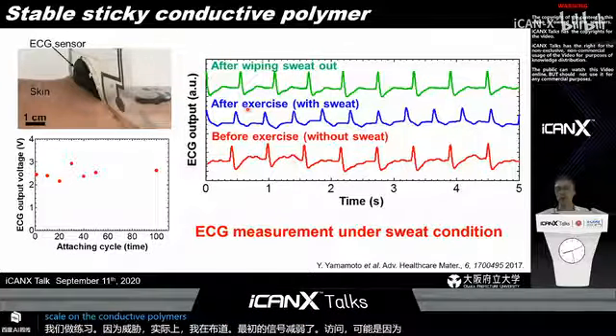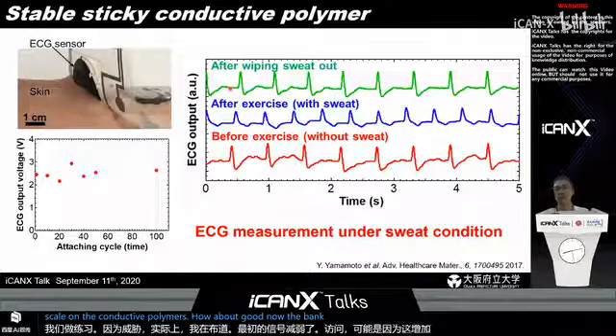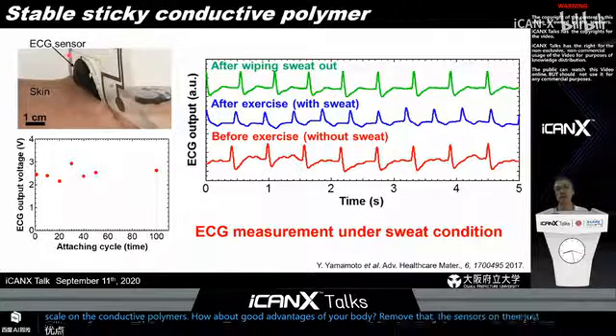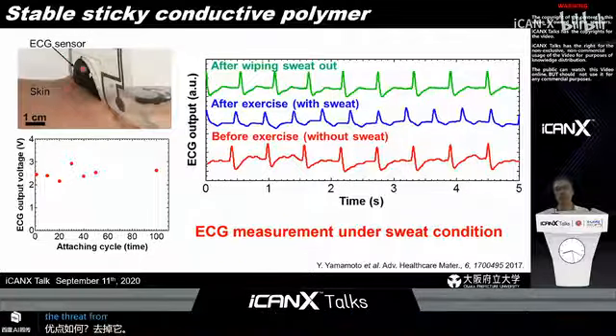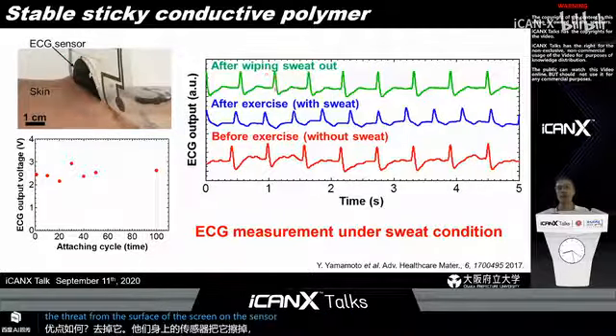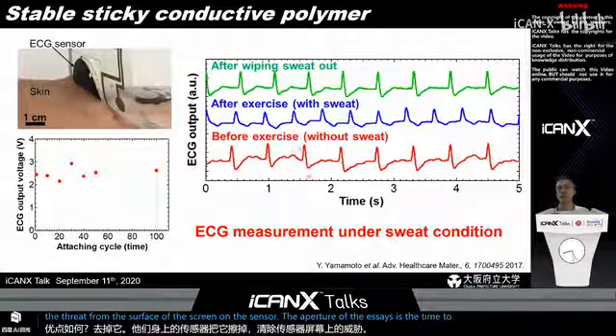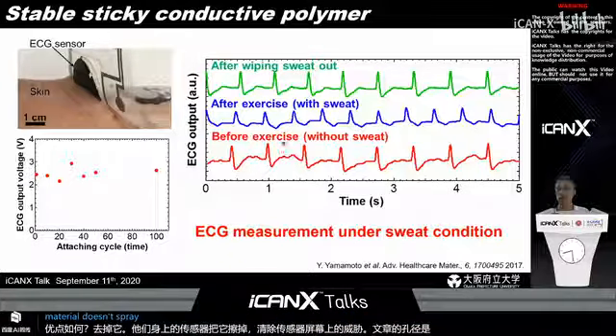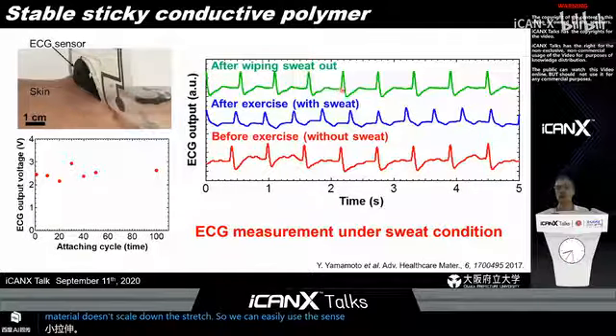However, the advantage is that after we remove this sensor and just wipe the sweat from the surface of the skin and the sensor, the amplitude of the ECG returns to the initial value. That means this material doesn't swell with the sweat, so we can easily use the sensor without any problem about the sweat.